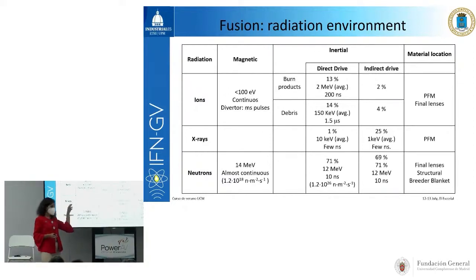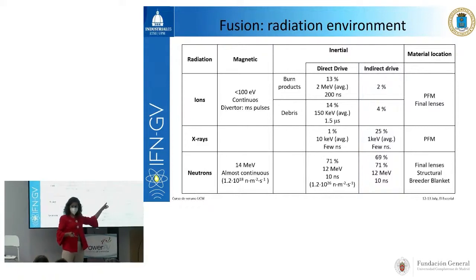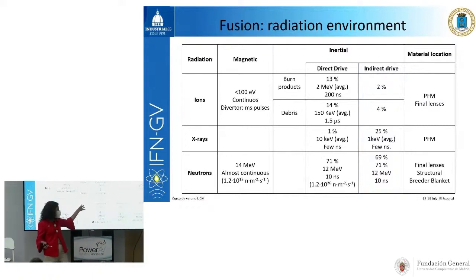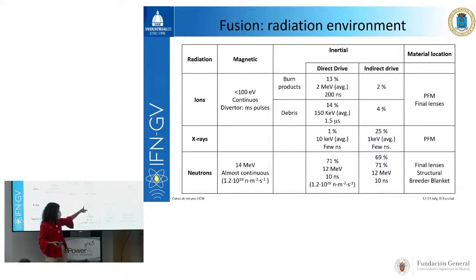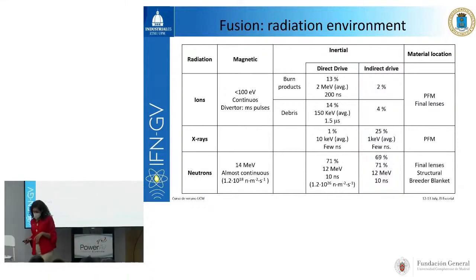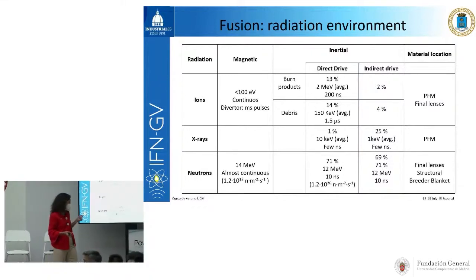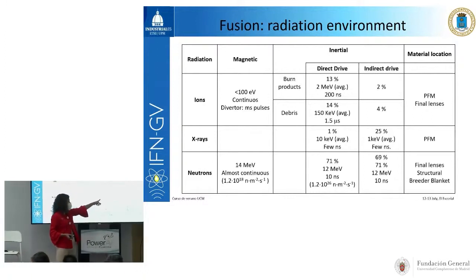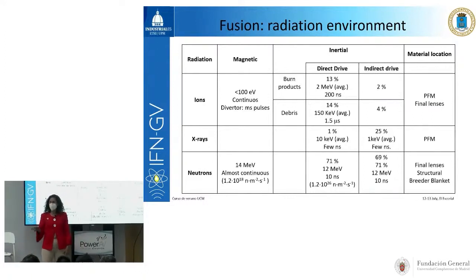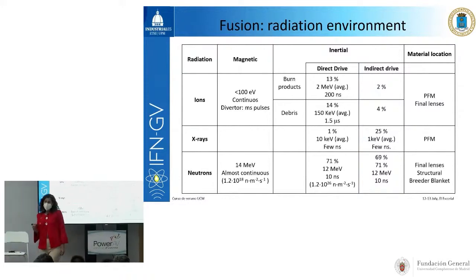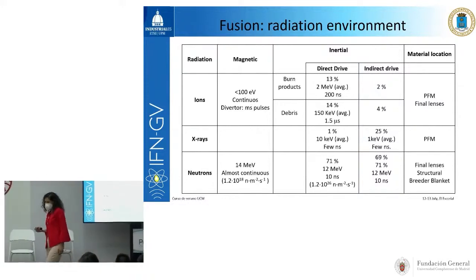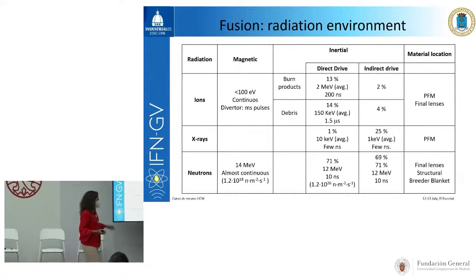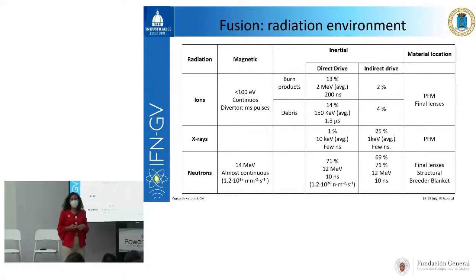Then we are going to have X-ray when dealing with inertial fusion, okay? Dimitri Batani was explaining this morning. And this X-ray is going to have an energy of around 10 keV on average in the direct drive configuration, and the pulse duration is going to be in the range of a few nanoseconds. And they are going to be especially deleterious in the case of the indirect drive configuration, okay, because a large amount of X-ray are produced out of the hohlraum, okay?